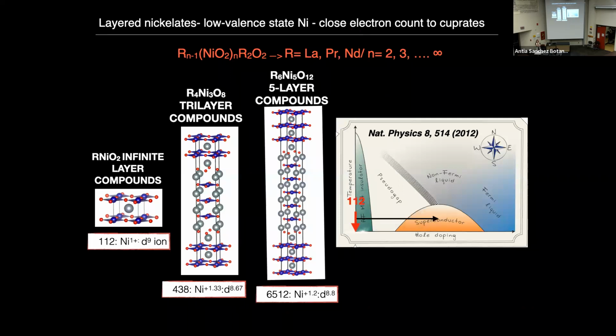That may not tell you anything, so let me come back to the cuprate phase diagram to see where all of these systems sit. The 112 material, as you saw before, falls at the corner. You then hole dope it, bring it into the dome area of filling. That's where superconductivity has been found. The tri-layer material instead falls into the overdoped regime, where in principle, if a naive one-to-one analogy to the cuprates were to work, you would expect to be finding a metal.